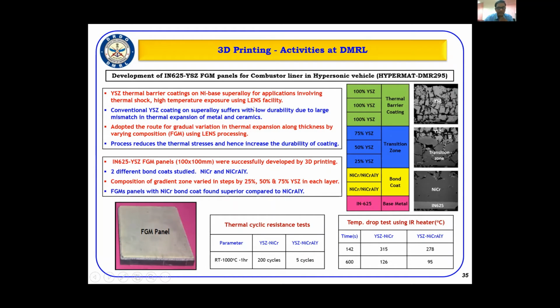The conventional YSZ coating, when applied on the normal superalloy, was suffering from low durability because of the large mismatch of thermal expansion between metal and ceramic. Due to this, the coating was failing, and then we adopted this route of 3D printing or direct energy deposition. Using this technology, a gradual variation of thermal expansion was attained along the thickness by varying the composition of the FGM using LENS processing. This process has reduced the thermal stresses and hence increased the durability of the coating. Initially, we successfully developed and demonstrated the coating for 100 by 100 mm. We used 2 different bond coats on the substrate of 625 alloy, and the ceramic composition was varied from 25, 50, 75, and 100, so that a gradual variation of the coefficient of thermal expansion was obtained. These were subjected to thermal cyclic resistance tests and met our requirements.